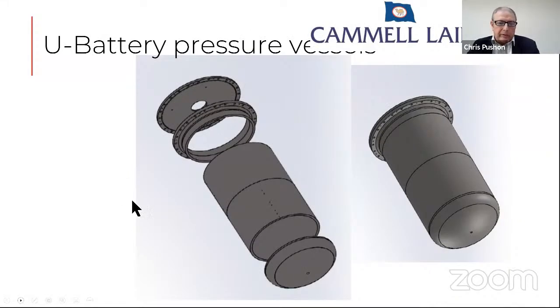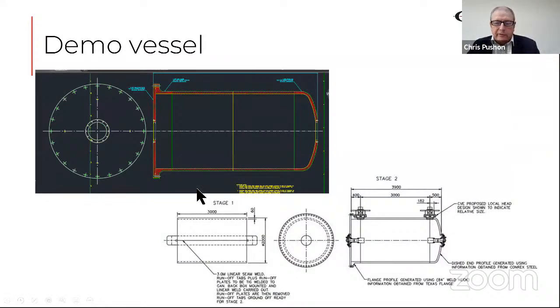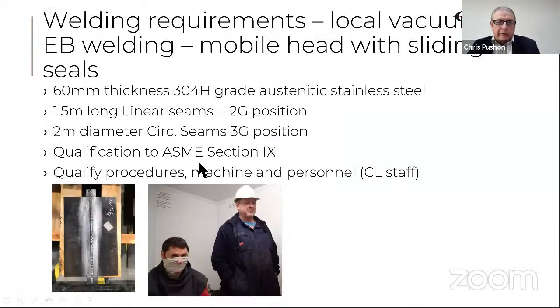And this was to be produced in 304H grade austenitic stainless steel with a wall thickness of 60 millimeters. And part of the requirement was that we would weld linear seams, so 2G position, horizontal, vertical, as well as making circumferential seams in the vertical up or 3G position. And the aim was to qualify these weld procedures to the requirements of ASME Section 9, but also to qualify the machine and the personnel.